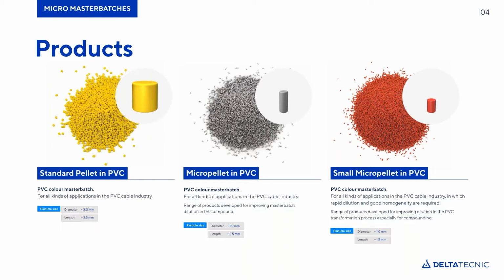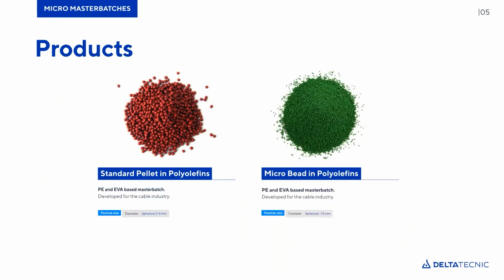The first and the second, the standard pellet and the micro pellet, are to be used at the extrusion line, at the dosing unit at the extrusion line, and the small micro pellet may be used for those cable manufacturers who produce their own compounds at their compound mixing station. If we go to polyolefins, to polyethylene or EVA-based Masterbatches, we have 2 products that are destined to the cable industry. One is the standard pellet in polyolefins.